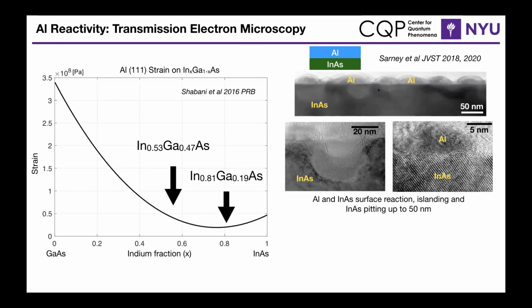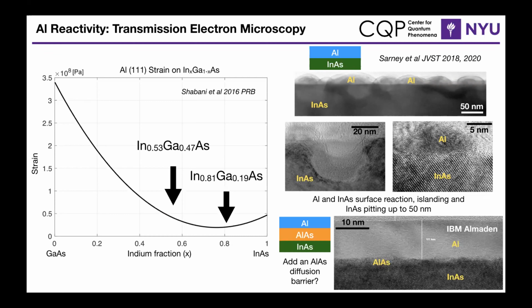So we've conducted these types of studies before where we've grown aluminum directly on indium arsenide, and we found that you have this really large reaction between the aluminum and indium arsenide layers. You get this aluminum islanding on the order of 50 nanometers and indium arsenide pitting of about the same size. And yeah, this just signifies that there's a large reaction between these two layers, and this is not ideal.